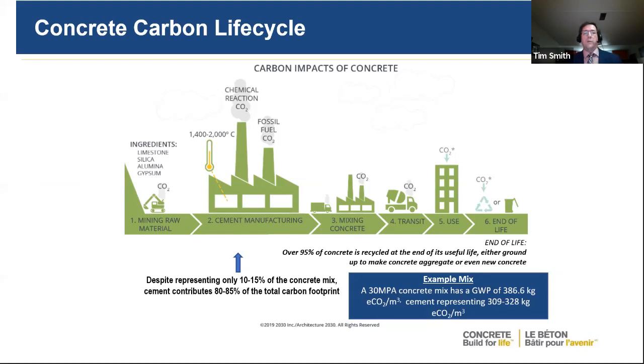So the first thing, I think it's important to give a bit of a background on concrete's carbon life cycle. You have the raw materials that you need for your concrete and for your cement. You then have your cement manufacturing. You have your mixing of the concrete. You have the transportation of the concrete to the job site. You have the use phase of whatever product that you've done, whether building a bridge or a pavement. Then you have the end of life of your product. Now, 95% of concrete actually is being recycled at this time at the end of its useful life. It is either being used back in as a granular base or actually back into new concrete.